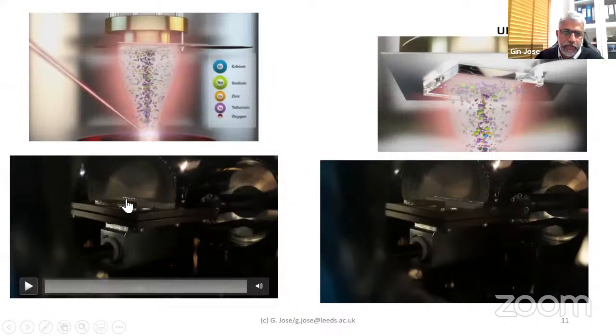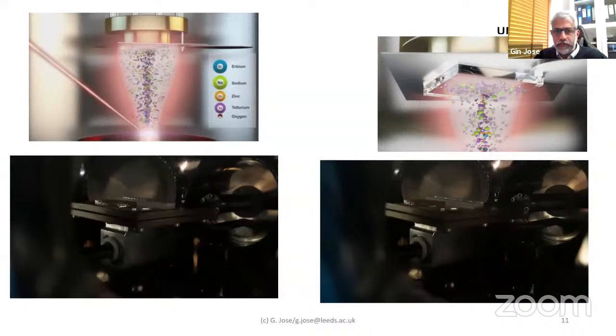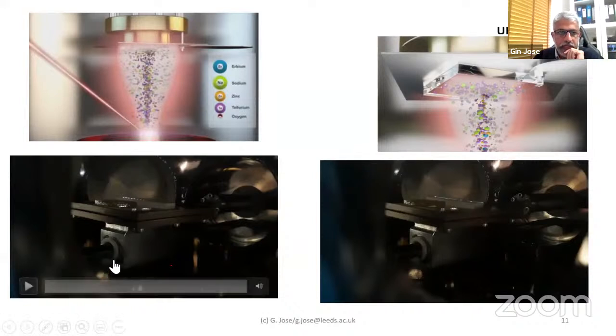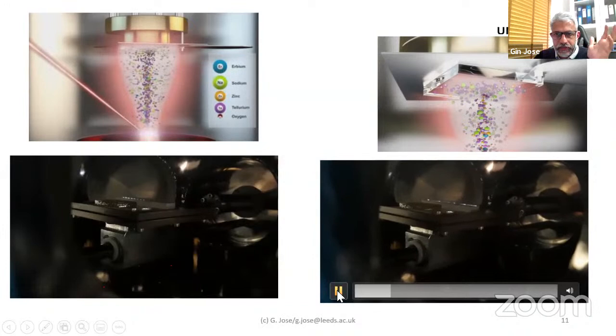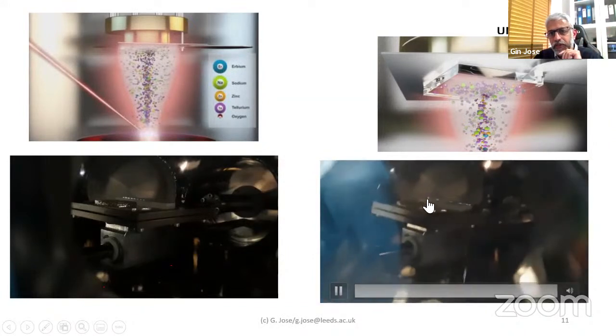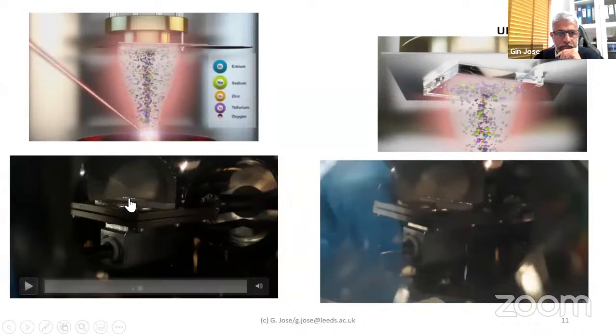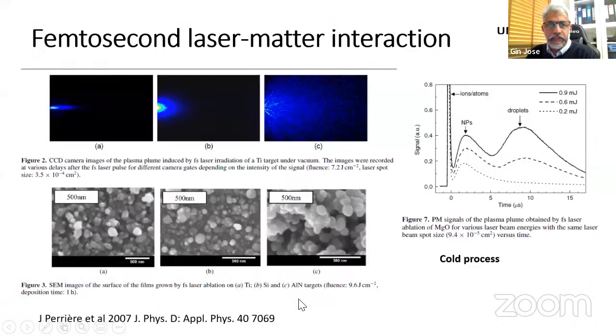If you focus on one point, it ablates from there, and basically you drill a hole. So you want to continuously ablate smoothly across. You have to move the target across the laser beam, and also scan the laser beam in the perpendicular direction, to get a uniform ablation of the target. Then you have the substrate over it, where the material is getting deposited. You can increase the repetition rate of the laser, so you get a nearly continuous plasma plume from the target. That white spot is where the laser is focused. It's a simple video showing how the material is getting ablated.